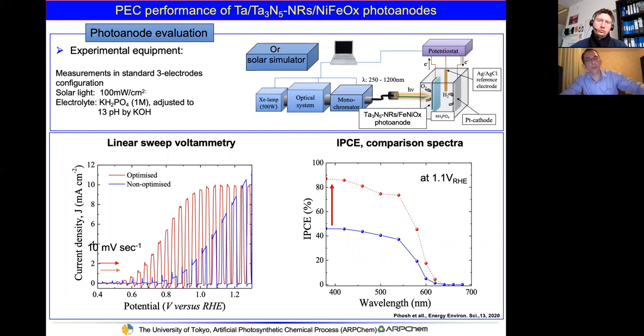And then we started to evaluate the performance of this material, optimized and non-optimized. As you can see, the non-optimized photoanode shows at 1.2 volt versus RHE about 10 milliamperes of photocurrent. However, the fill factor is very bad. On the other hand, the optimized photoanode shows an excellent fill factor, and also the saturated photocurrent, which saturated around 10 milliamperes at an applied voltage of about 1 volt. So it's really excellent.